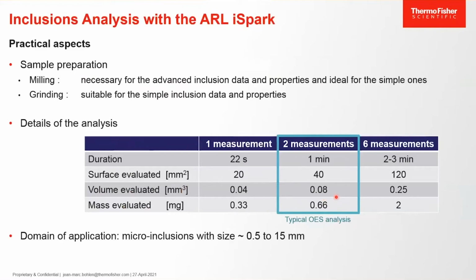Finally, I want to mention that the domain of application is limited to micro inclusions with size of about 0.5 to 15 micrometers, excuse me, the typo, micrometers, depending on the type of inclusion and the sample. So there is no way to look at macro inclusions with the Spark OES.